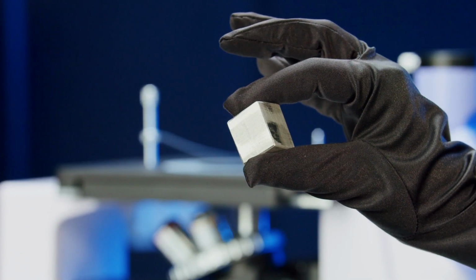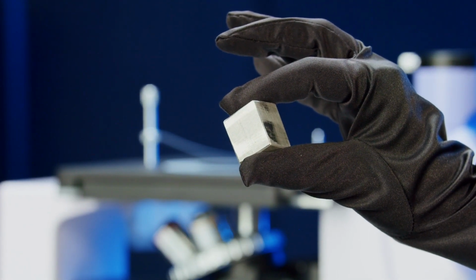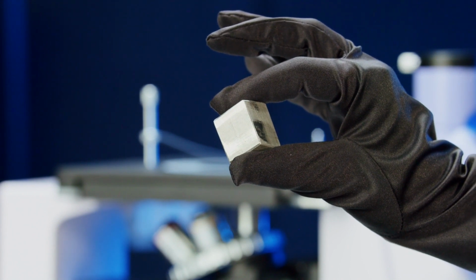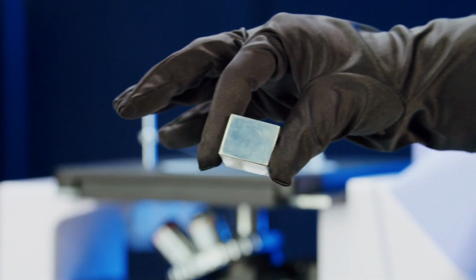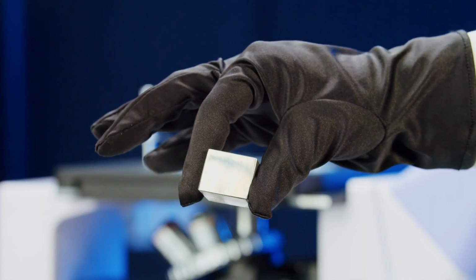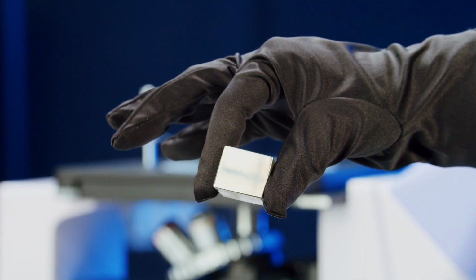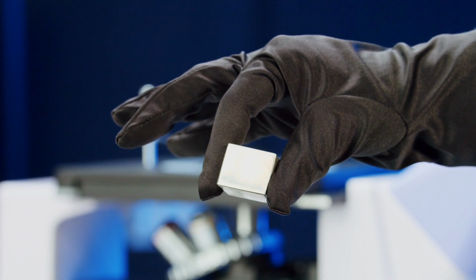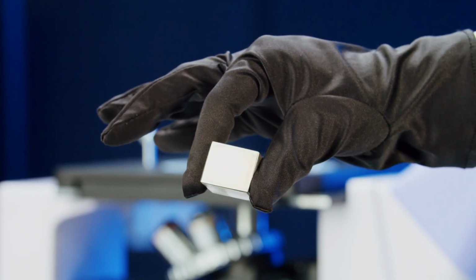Next comes grinding, gradually reducing roughness using abrasives of different grit sizes. The next step is polishing, bringing the surface to a mirror-like shine. At this stage, inclusions become visible. They do not get polished and appear as dark spots.